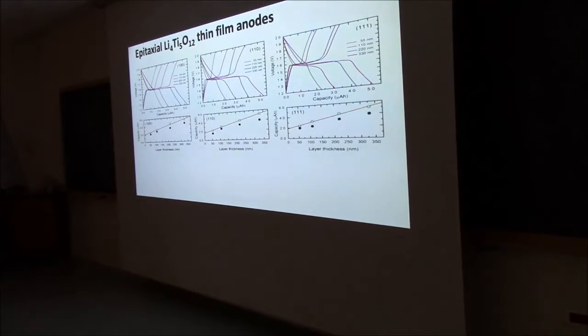Everything else is a bulk effect. More material, you store more lithium. That's an offset. And that's something which you can only do if you have this control. You can show, okay, how much is there? And is there a difference between them? What you can see is that it's not so much different between them. There's a slight difference, but that's also because of some of the differences in surface morphology.